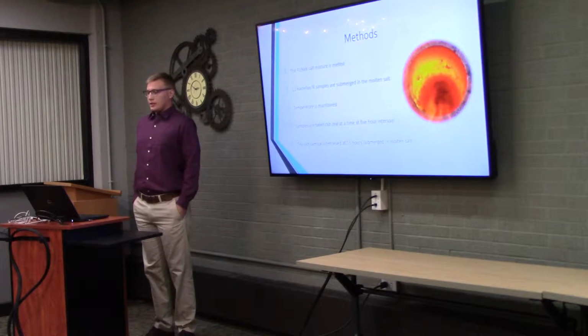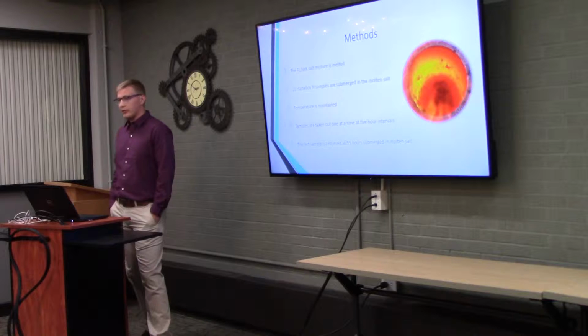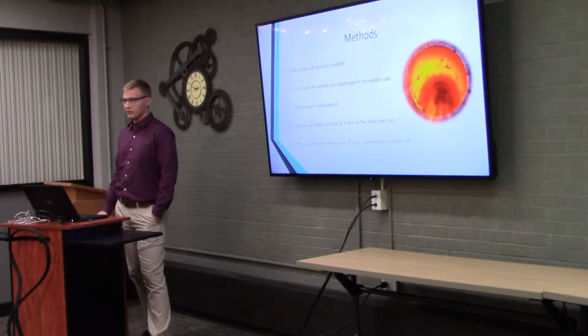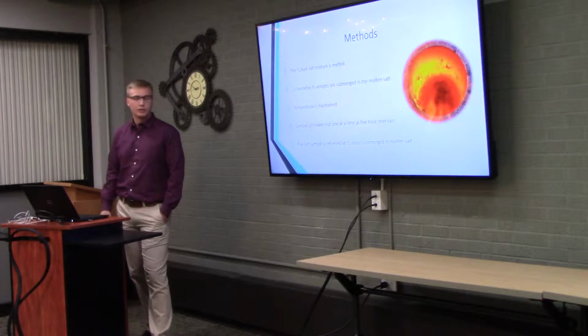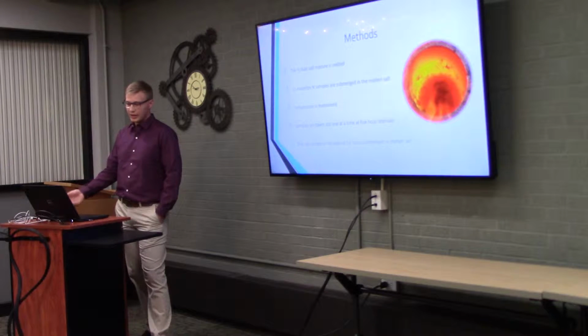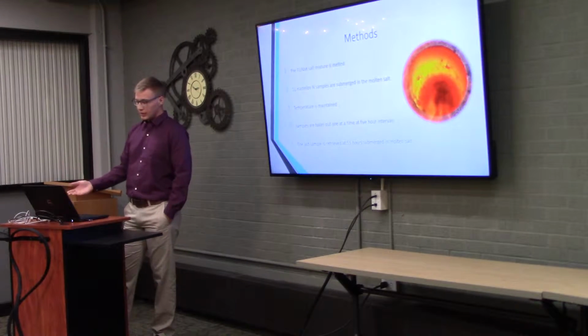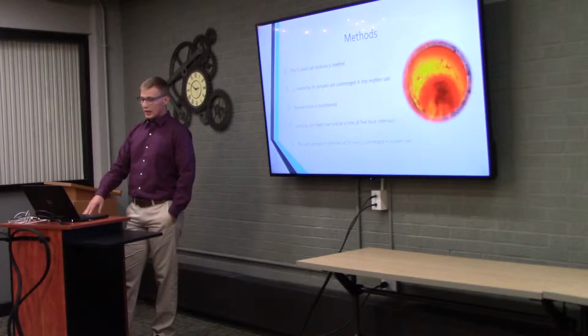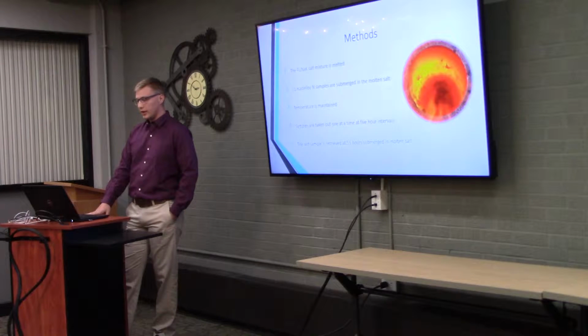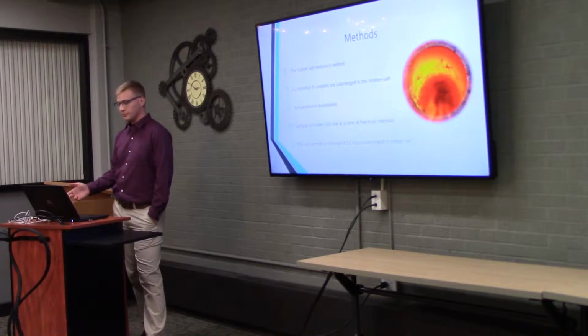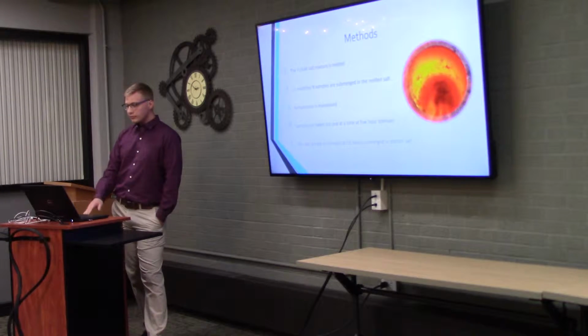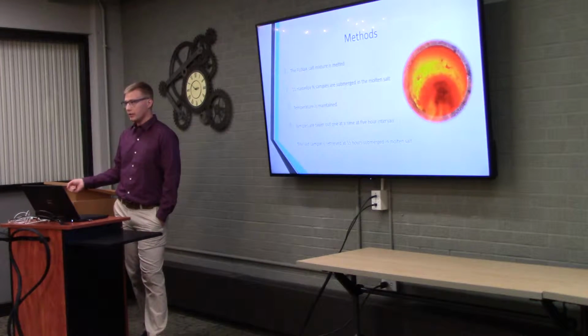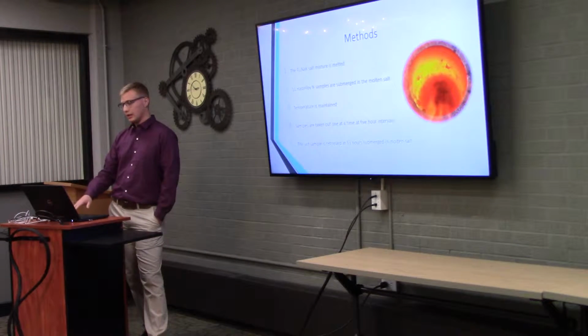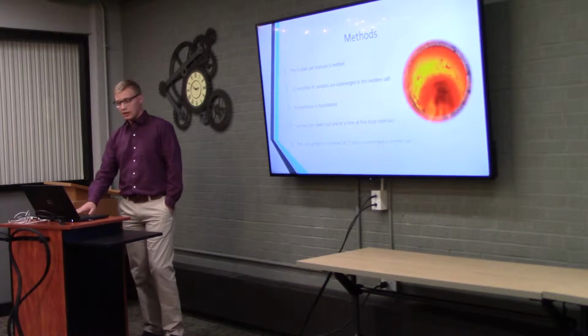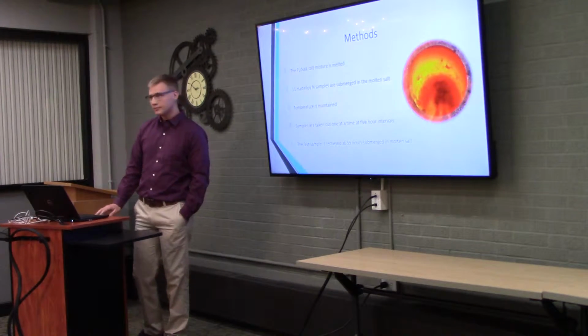So my methods for this, the first thing I had to do was melt the FLiNaK salt mixture. And I did this using essentially a charcoal foundry that I built with a shop vac for forced airflow to keep the heat consistent and high. And after this was melted and mixed, I placed 11 Hastelloy N samples in that molten salt, and then I maintained the temperature to keep the salt liquid. And then I took the samples out one at a time at 5-hour intervals. So the last sample was taken out at 55 hours submerged in the molten salt. And after that, I took this cool picture of the melted salt.